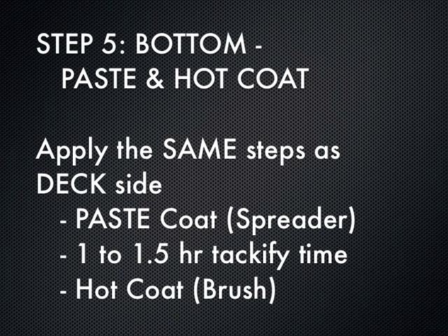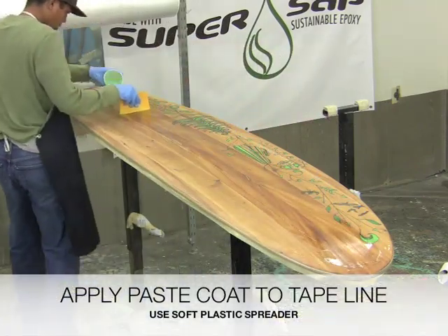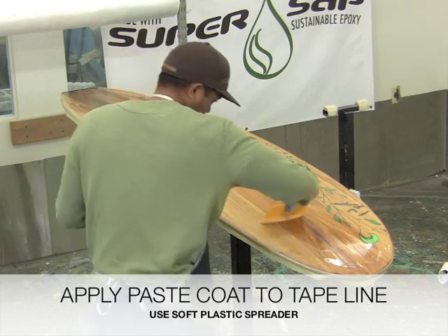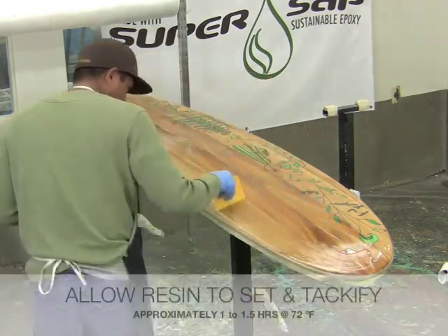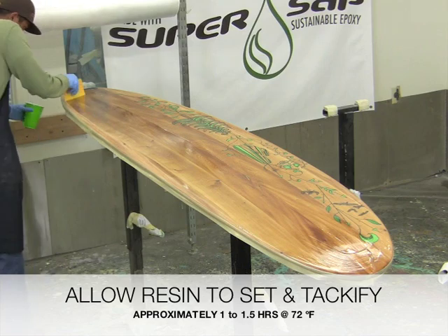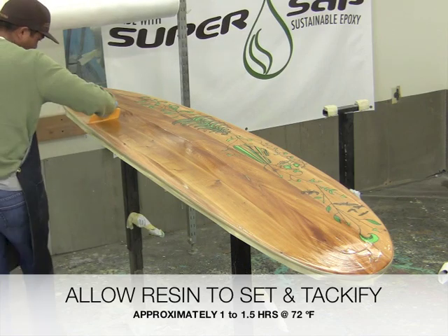Similar to the deck side, we're going to apply a paste coat or squeegee coat before applying our brushed hot coat. Lay down a thin, even layer of resin, ensuring that the resin gets into the tape line, and then allow the paste coat to set and tackify, but not fully cure.